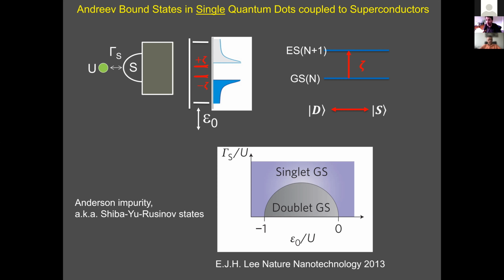And you can solve it analytically, I believe, but people have also done numerical calculations, things like that. And so what this model produces is in the spectrum of the system where you have a gap. So this is a superconductor, has a gap. And on the dot, on the energy side, you have some levels, but this interaction generates additional levels inside the gap. So energy levels of the dot get pulled into the gap and create these particle-hole symmetric levels due to superconductivity, which are denoted by these red letters, whatever they are.